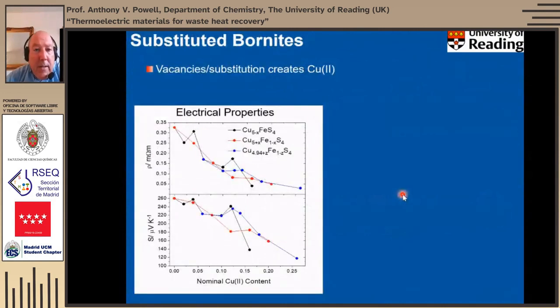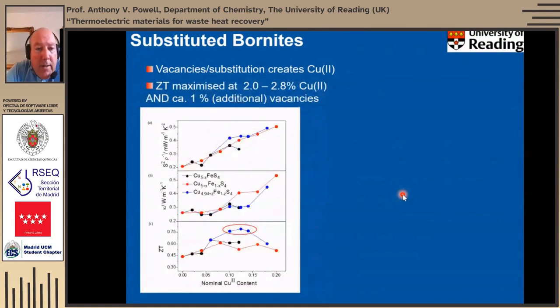Interestingly, the electrical properties and the Seebeck coefficients, regardless of which series we take, so these are the 3 different series I've just mentioned, they seem to follow a common curve. And in fact, the power factor seems to scale almost linearly with the copper-2 content. So as I say, each time we're doing these changes, we're trying to modify the copper-2 content to introduce some more holes. We see that we increase the power factor in an almost linear fashion with the copper-2 content. However, to get the maximum performance, this is where we get the highest ZTs here, it's important that we don't just have the optimized copper-2 content, which is about 2 to 3%, but we also need those additional vacancies.